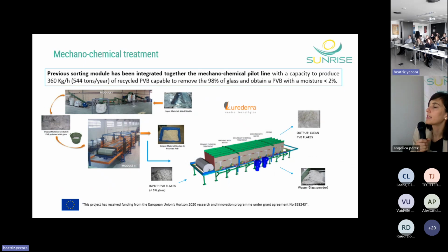So after sorting these categories, what we do is a mechanochemical treatment. Usually laminated glass recyclers make a mechanical recycling. So we introduce here an additional chemical step to remove a higher part of the glass. We have optimized this procedure to improve the removal of glass in the high quality categories, which is more important. And this chemical treatment consists of different washing steps where different agents are eliminating the glass and breaking the links between the glass and the PVB to remove this glass.